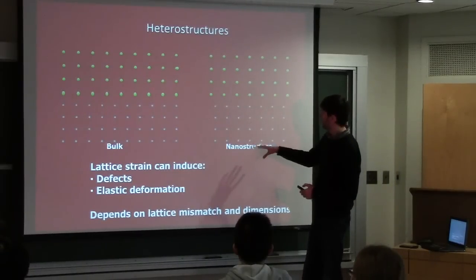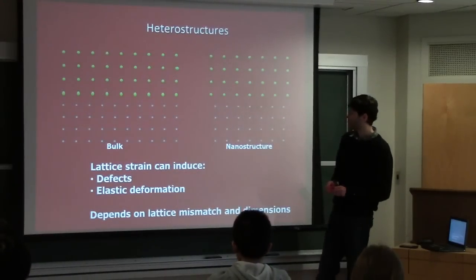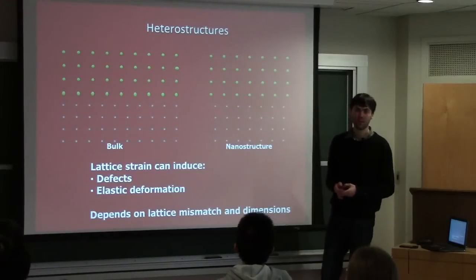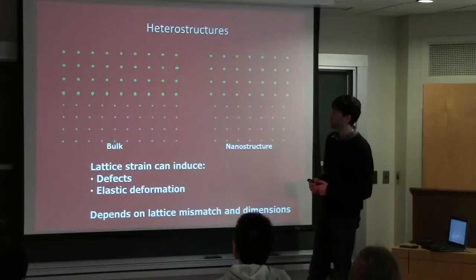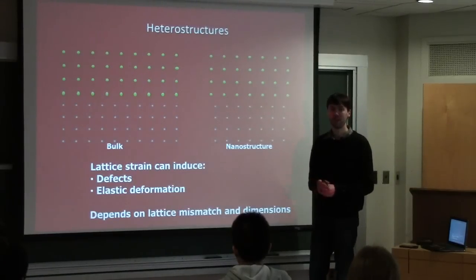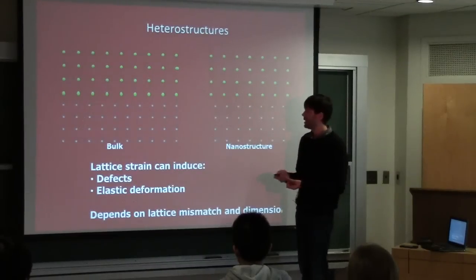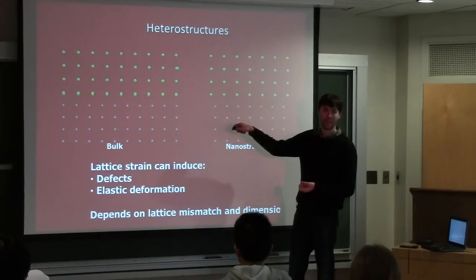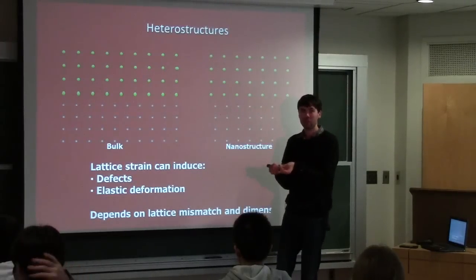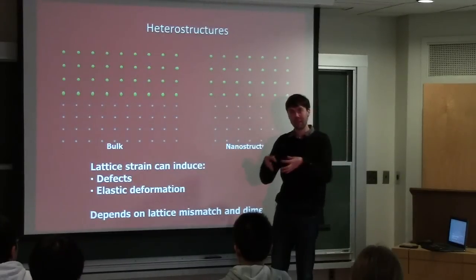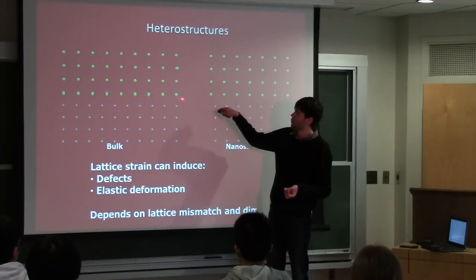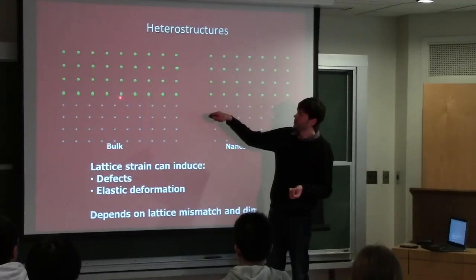And these one-dimensional nanowire structures also have an interesting advantage over bulk growth related to defects. You see, in the bulk, when you grow 2D films, it's much easier to create defects. That's because, for example, if you want to grow one semiconductor on top of the other, and they are a bit mismatched, this is now an infinite surface from the point of view of single atoms. And so the strain that you build into this structure has nowhere to go. It stays in, and then it produces various defects. For example, here, to maintain this lattice above, the system decided to skip one bond. So this is a defect.